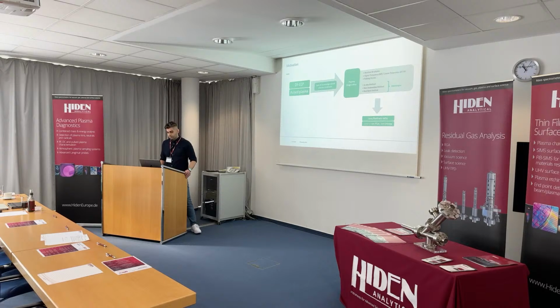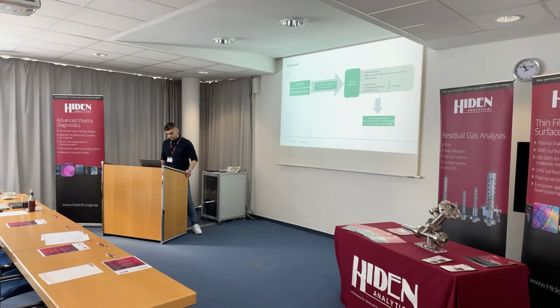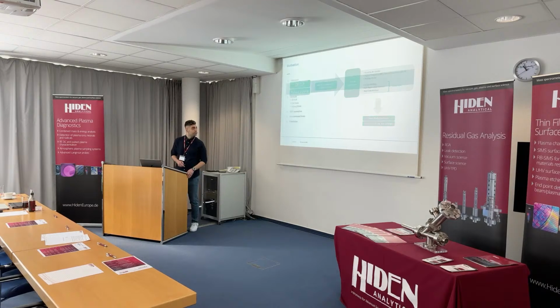I start with argon plasma because it's simple and it doesn't degrade the tool itself. And I did some higher frequency and lower frequency variations, and I did experiments on pulsed plasma mode. And the advantages are it's an in situ method, non-destructive, and real-time. And it gives us insight on ion per radical ratio and control over ion flux and ion energy.